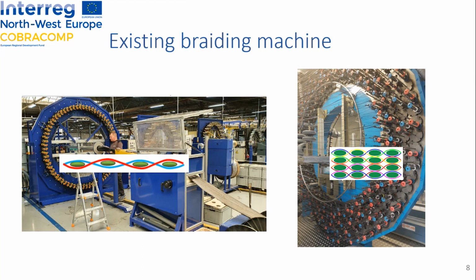So the monolayer machine is used with 144 bobbins and 72 positions for UD yarns. And for the multi-layer interlock braiding machine, we use 256 bobbins and the same quantity of unidirectional yarns. Normally in this project, it was planned to modify this machine to increase the quantity of unidirectional yarns we can fill in the braid reinforcement, but this step has been cancelled. So we only work with this existing machine without modification.